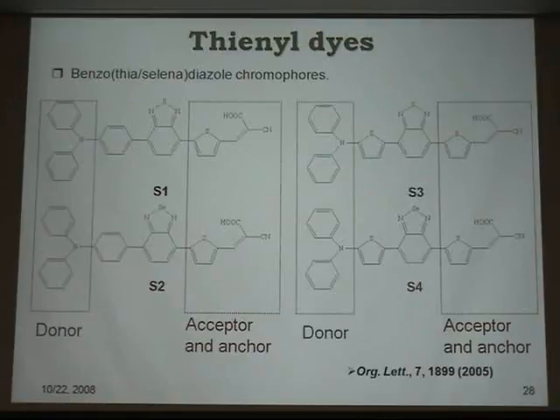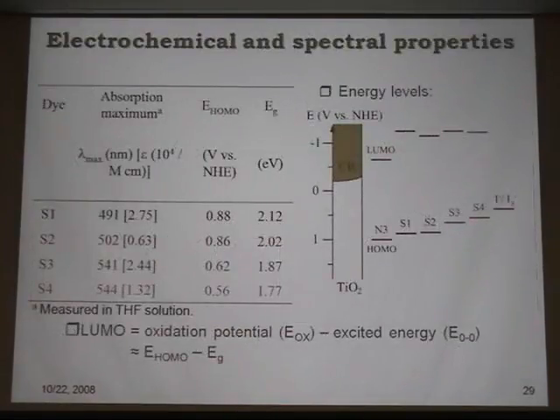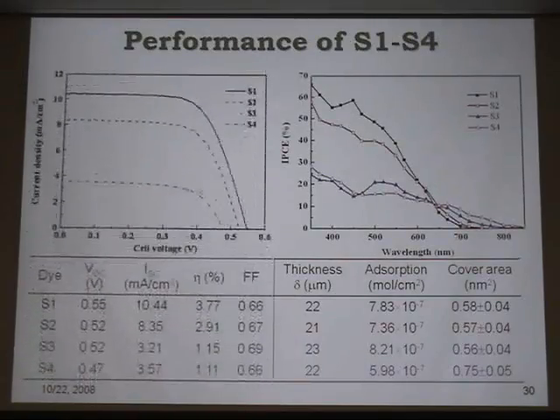Now, with the thienyl dyes, we have 4 dyes which we synthesized, all with the same ending group. But here you have thiophene, here you have benzene, and here the difference is selenium, but this is sulfur. So again, we tried to find the HOMO-LUMO and decided that maybe dye number 4, S4, will give the best performance in terms of HOMO-LUMO band gap. However, if you look at the cell performance, S4 did not perform the best, but S1 here and here are consistent. Always S1 gives the best performance.